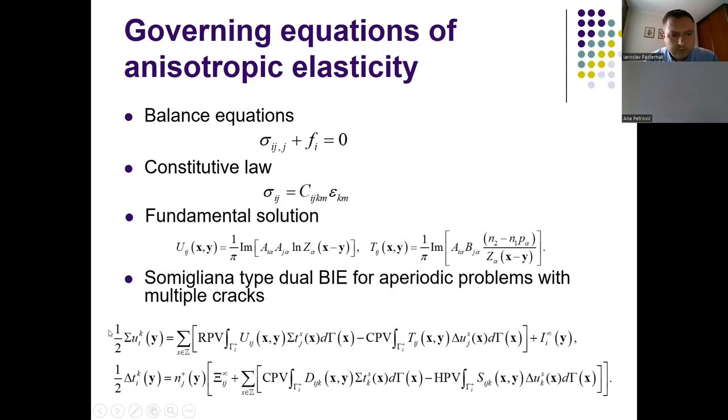The dual boundary element equations are written at the end of the slide. The first is a displacement boundary integral equation and the second is the traction one. We have to consider both because we have to consider the displacements at each side of the crack.